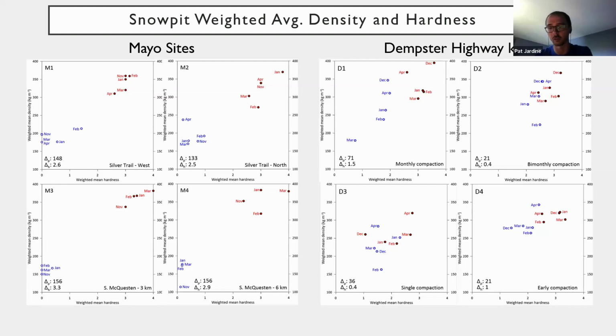At the Dempster, natural snow conditions were harder and more dense, and with greater variance. Generally, the snow had a hardness of about 2 and an average density of about 270 kilograms per cubic meter before compaction. And after compaction, the average hardness rose to about 3 and the density rose to about 311 kilograms per cubic meter on average. Even though the initial snow conditions were very different, after compaction, the snowpack physical properties were pretty similar.